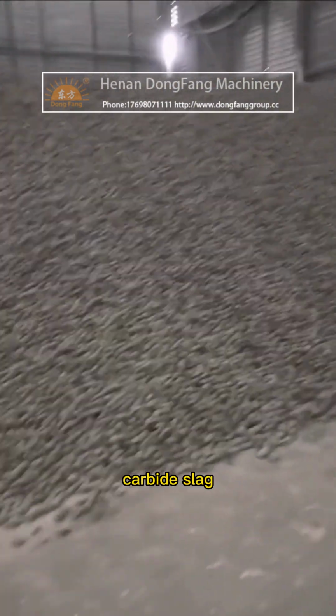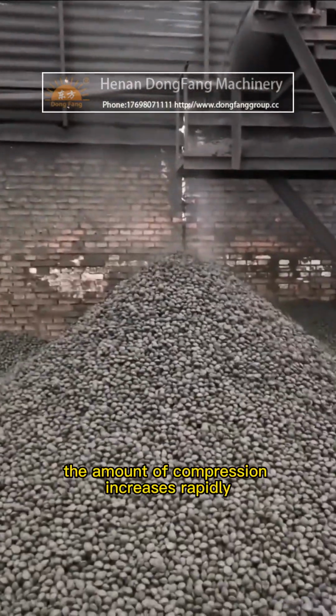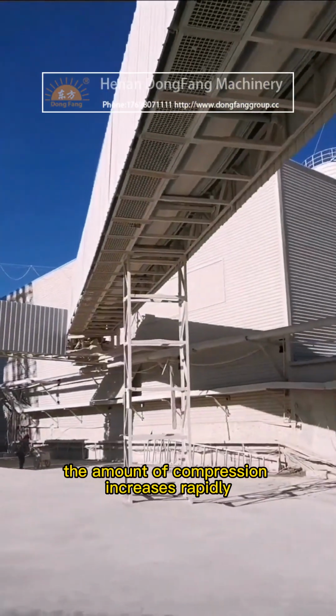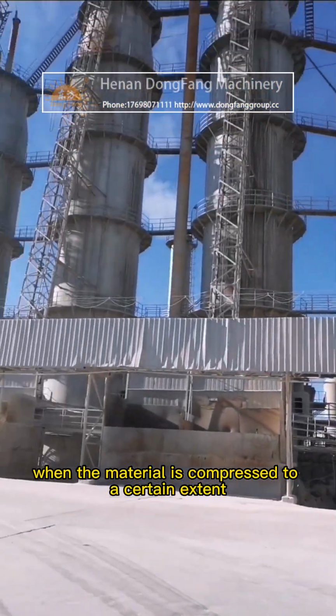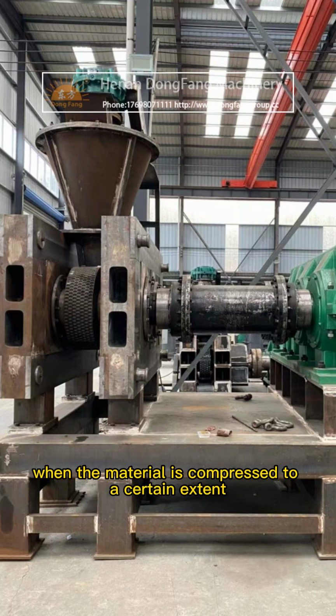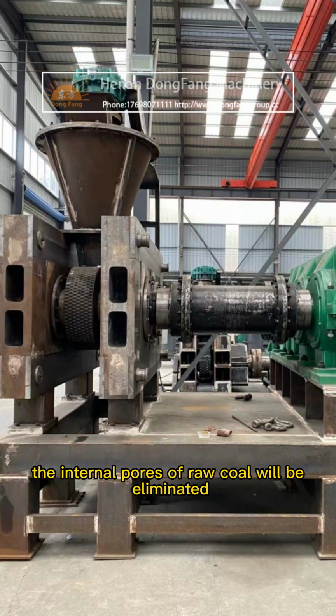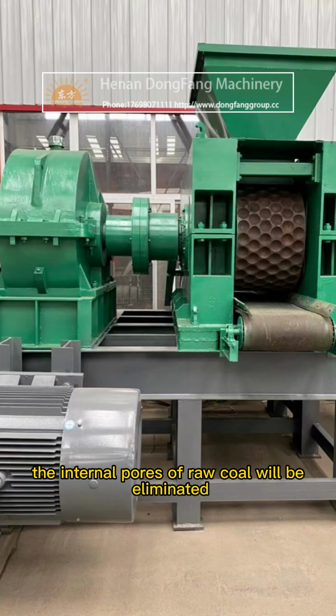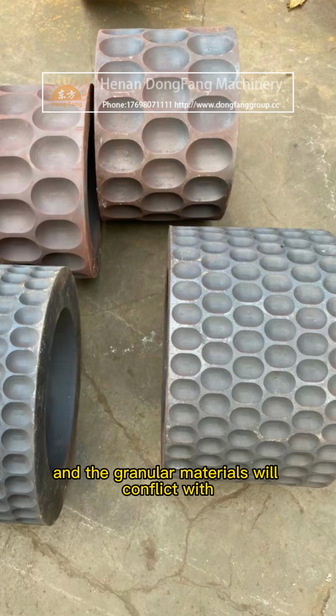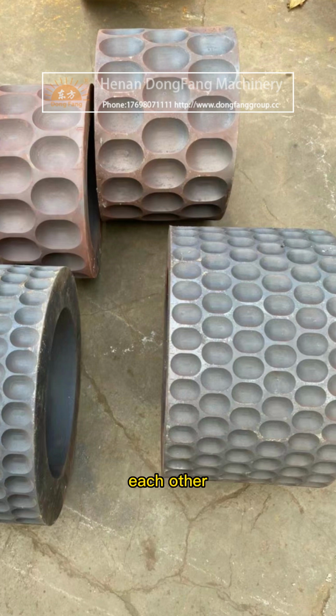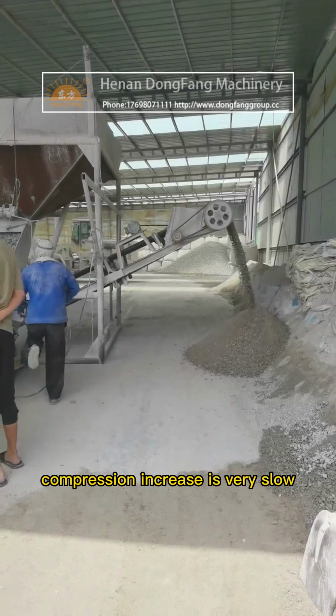The test curve of the carbide slag ball press shows that there are large pores in the original carbide slag at the beginning of pressure. The amount of compression increases rapidly. When the material is compressed to a certain extent, the internal pores of the raw material will be eliminated, and the granular materials will conflict with each other. Compression increase is very slow.